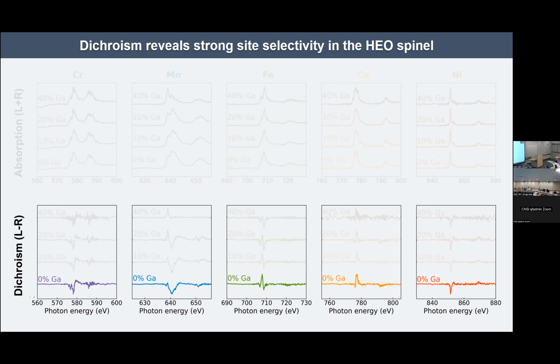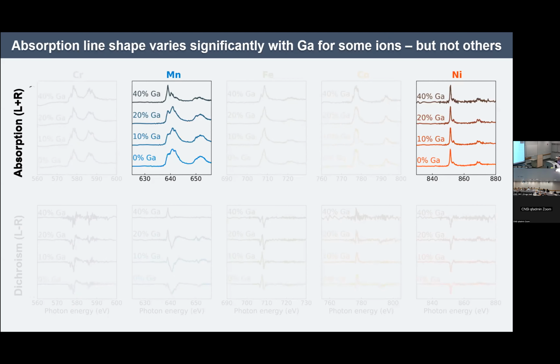And so we can see right away, the fact that these signals are not flat must mean that each of our elements has a preference for which site it's occupying. So iron in green and cobalt in yellow are preferentially occupying our tetrahedral sites, and the other 3 are preferentially occupying the octahedral sites. Next, we can look at what happens when we begin to throw gallium into the mix.